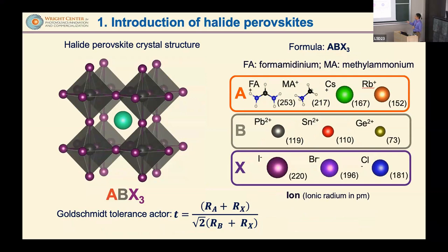And then you have another larger cation, either cesium or an organic cation, because in order to form the structure this cation must be large enough, since the lead and iodine atoms are too big. There's a formula we call the tolerance factor to describe the stability of this structure. That means not all elements coming together will form the structure. There are requirements on the size of the atoms in order for them to form this.